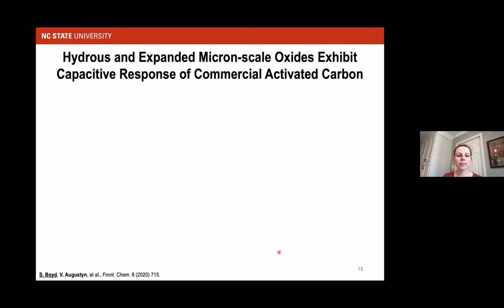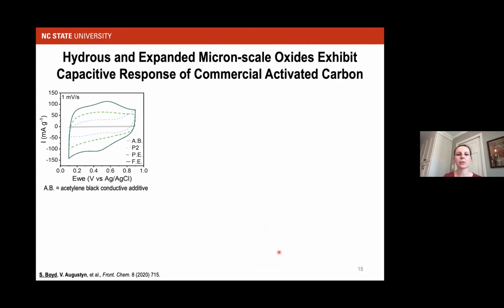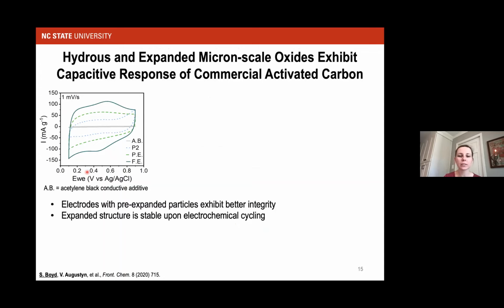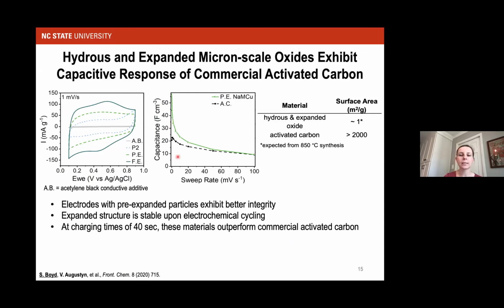Okay. So the cool thing is that when we take those materials and assemble them into an electrode, a slurry electrode, now we see that the capacitive response is there, and it's very, very reversible. They can cycle for thousands of cycles, and their capacitance is actually very similar to the commercial activated carbon used for electrochemical capacitors, which is surprising because we start with a material that has orders of magnitude lower surface area than activated carbon. Remember, we start with a material that's a 900 degrees Celsius synthesis of an oxide, and now we're getting a capacitive response that's like that of activated carbon.